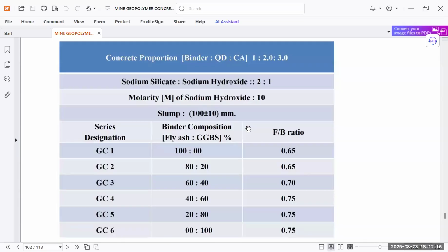We are making a molarity solution. In this case, we are not using water also, but we are changing different compositions, like the fluid to binder ratio, and the fly ash to GGBS ratio. This cementitious material can be GGBS or a different source. So the slump also we are keeping at 100 plus or minus 10 mm.